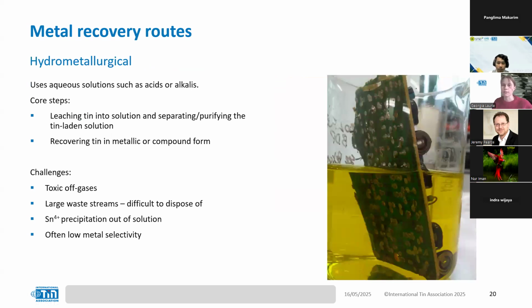One of the major metal recovery routes is hydrometallurgy. This involves using aqueous solutions such as acids or alkalis to recover metals from e-waste. The core steps usually involve leaching tin into solution, then separating and purifying the tin-laden solution to recover the tin. Leaching tin from e-waste using acidic solutions requires careful reaction conditions. Actually, simple acids alone can sometimes struggle with leaching tin, and it's found that using an oxidant improves the solubility of tin ions.